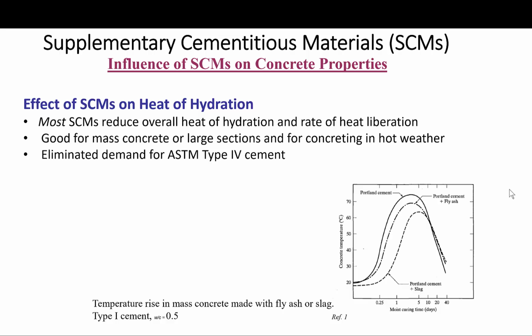Anyway, although the heat of hydration of the pozzolanic reaction is generally considered to be low, it may actually be higher when normalized on a weight basis. Remember, we replace a lot of the cement with a mineral admixture, so we end up with lower heat overall and lower heat generation, but on a normalized basis it might be higher. But since the reaction is slow, the heat is released slowly, and the temperature rise in mass concrete is invariably reduced.